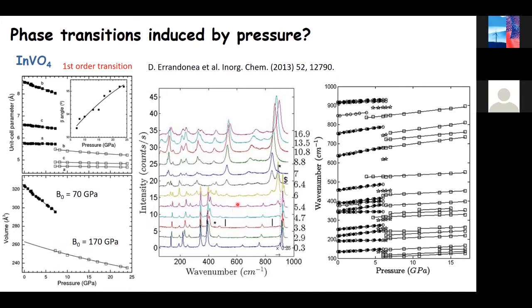Here you have results from Raman experiments. In the Raman experiments, again, we can identify this Raman spectrum with the low pressure phase. The low pressure phase has 18 Raman active modes, but when we keep going beyond 6 GPa, we start seeing changes which correspond to the change of the Raman spectrum from that of the orthorhombic structure to that of the monoclinic structure. You can see this probably more clearly here, where we plot the pressure dependence of Raman modes. Here you have the low pressure phase, and here you have the high pressure phase. And the change is very noticeable in the frequencies.